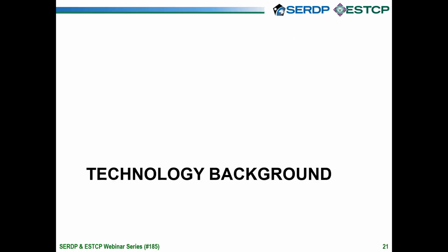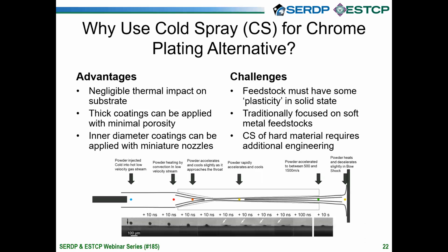So let's start with the technology background. Cold spray is a technology for consolidating metal powder. It works by adding metal powder to a heated gas stream, which is carried through a supersonic nozzle that accelerates the metal particles to very high velocities between 500 and 1500 meters per second. At those high velocities, the metal particles undergo extreme plastic deformation when they hit another metal surface. And that extreme deformation allows those particles to bond to the metal surface and to build up a thick coating over time.